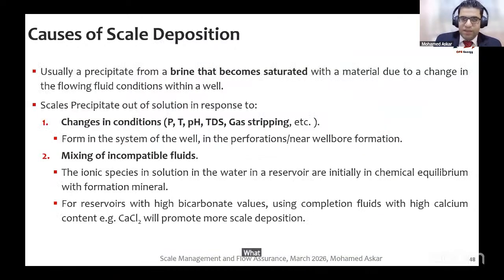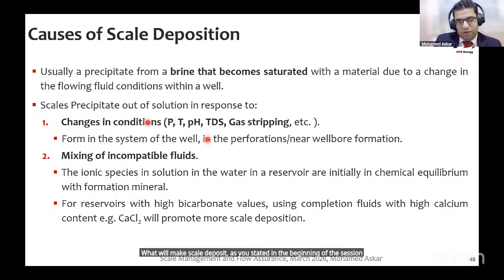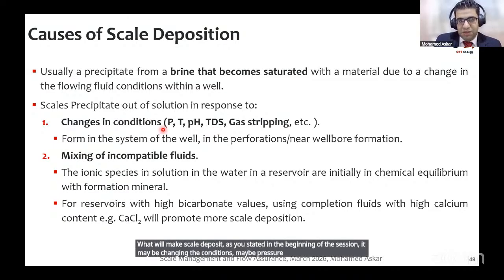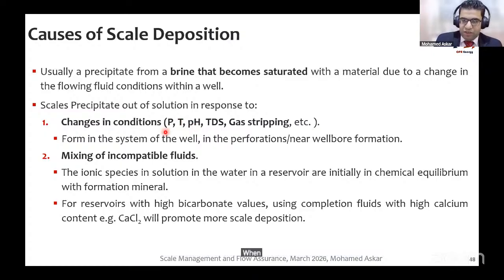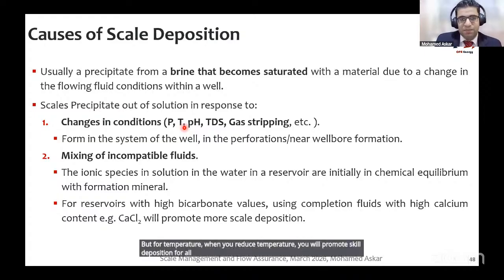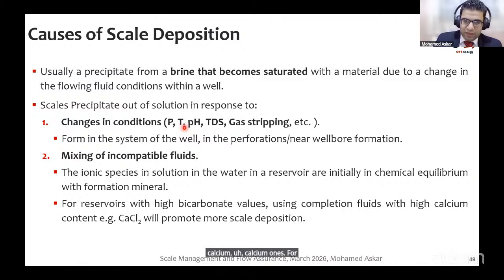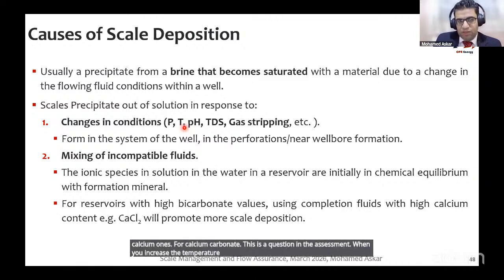What will make scale deposit? As you stated in the beginning of the session, it may be changing the conditions, maybe pressure reduction, temperature reduction, or pH reduction. When you reduce pressure, you will promote some scale deposition. But for temperature, when you reduce temperature, you will promote scale deposition for all types except calcium ones. For calcium carbonate, this is a question in the assessment. When you increase the temperature, you will promote scale deposition of calcium carbonate.